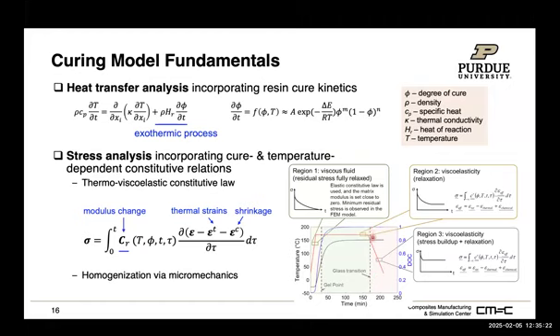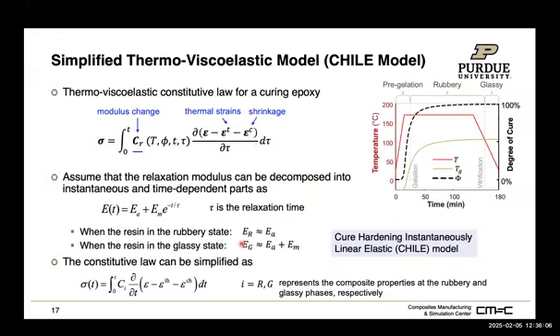But it is also being considered here because it's also under cooling, right? So mainly the polymer finishes the chemical reaction at a relatively high temperature and then cools down to build up stiffness. So in the whole process, we have to account for the modulus change as a function of time and degree of cure, which is your curing process, and also account for the thermal strain and the chemical strain, because when you form those cross-links, it actually will shrink. So those things need to be considered in the modeling framework. And also, as I mentioned earlier, there is the reinforcement, right? How we need to do the homogenization. So there are ways, with more detail, to incorporate all kinds of the phenomena I just described into this thermal viscoelastic framework.